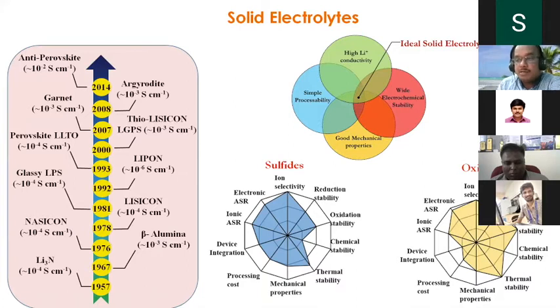These are the competitors for electrolytes for solid-state batteries. Sulfides are really quite good. The conductivity is so good, around 10 to the power minus 2 Siemens per centimeter. Compatibility with the electrodes is quite good. Wetting ability is so good. It has its disadvantages. Stability with metallic lithium is not so encouraging, and much more, there is a moisture problem. You cannot make this material in open conditions. Special sample preparation chambers are required. And it's very, very difficult for bulk production.